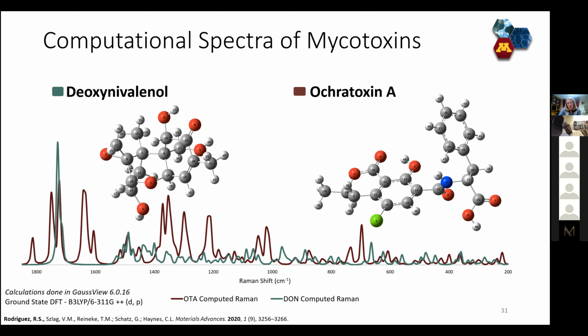And in fact, these spectra weren't published. So Becky did some computational work and predicted the vibrational spectra for the two molecules. The one for DON is in green, the one for ochratoxin is in that kind of reddish color. You'll see there is some overlap, but also some really distinct features. Having her do these calculations was also really helpful because when we later captured the spectra, it let us understand which parts of the molecule were closest to the surface or interacting with the polymer.